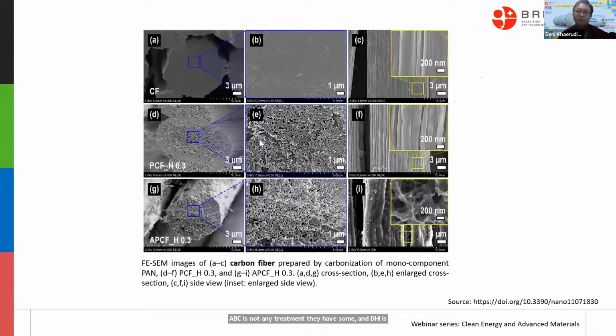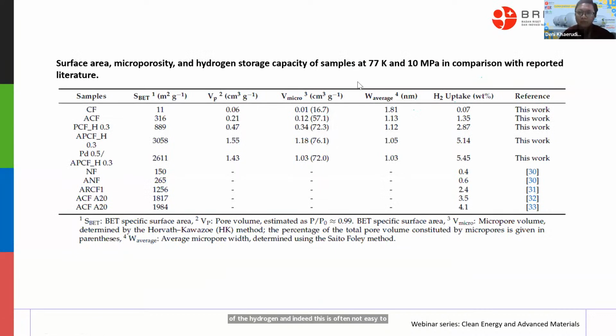So the pore size and pore distribution are different between the second line and the third line here, and also the pore size that developed between the original, the virgin one, and the last line. So for sure, the last line is the ideal one as the sorbent material for hydrogen. And indeed, this is not easy to achieve. Okay, I continue. So this is their condition.